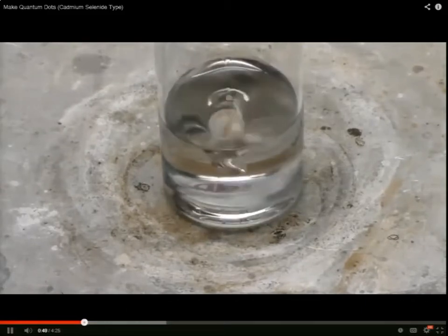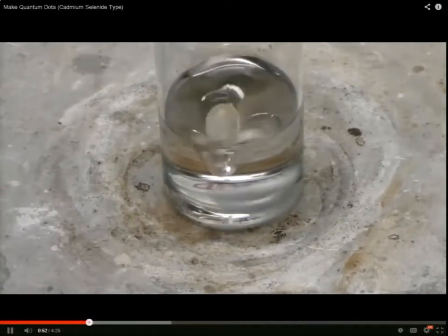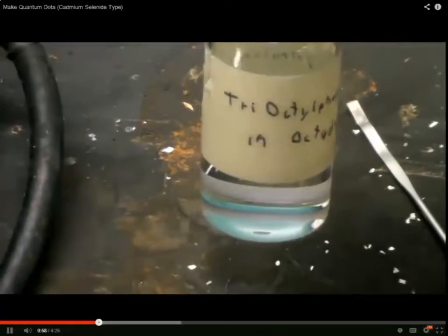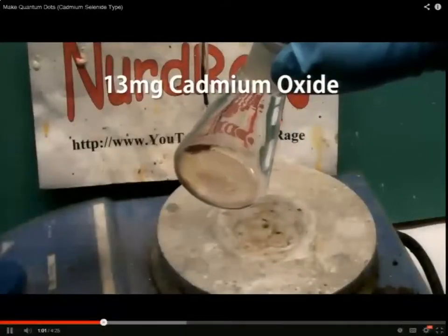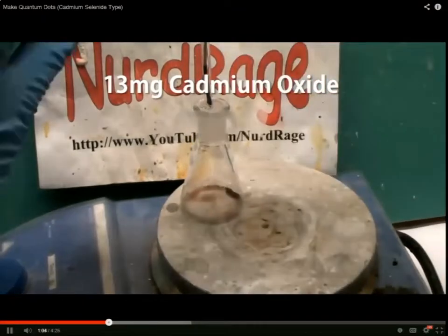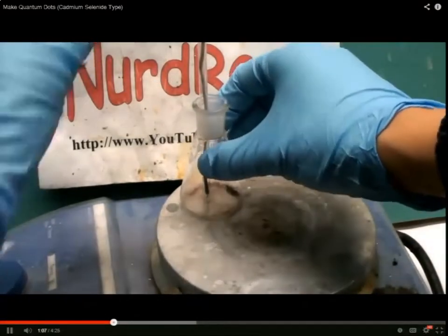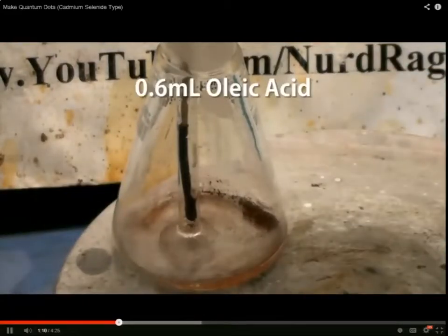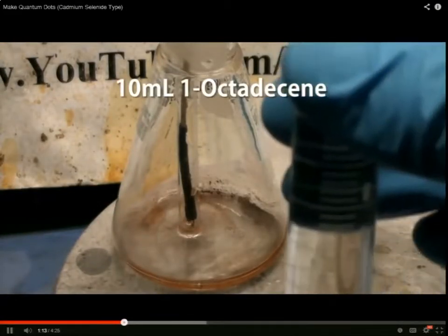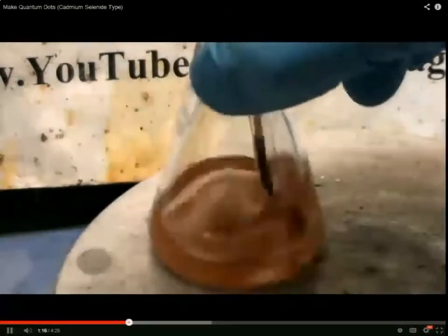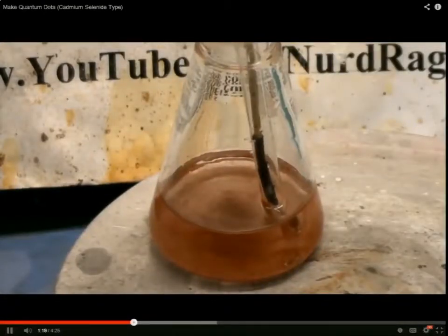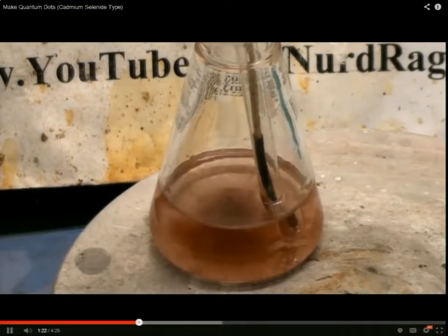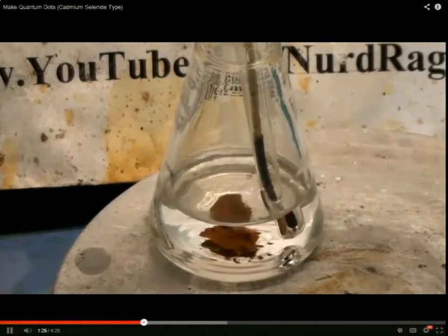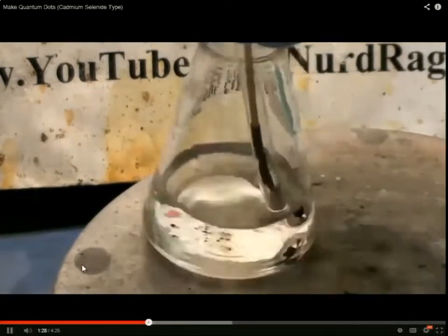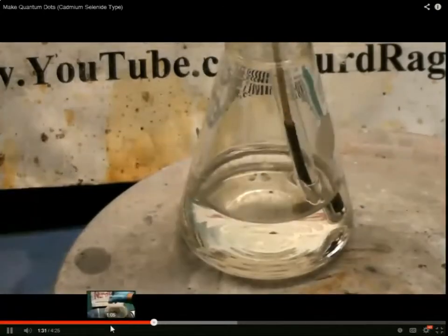What's happening is the trioctylphosphine is reacting with the selenium to form trioctylphosphine selenide. Once it's ready, seal it and let it cool. This will provide us with about 5 experiments worth. Now get 13 milligrams of cadmium oxide in a flask and place in a glass thermometer. Mine happens to be a glass encapsulated digital thermometer. Now add to it 0.6 milliliters of oleic acid and 10 milliliters of 1-octadecene. Now heat the mixture until the cadmium oxide completely dissolves. What's happening is the cadmium oxide is reacting with the oleic acid to form cadmium oleate. After the cadmium oxide dissolves, keep heating until the mixture hits 225 Celsius.